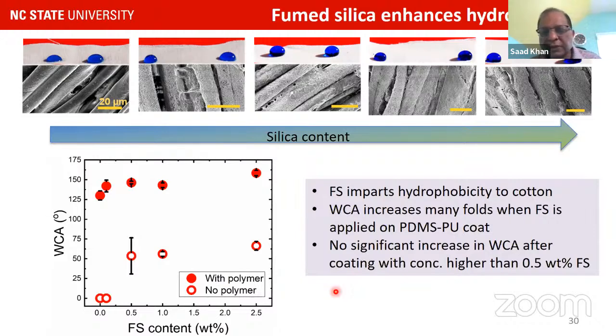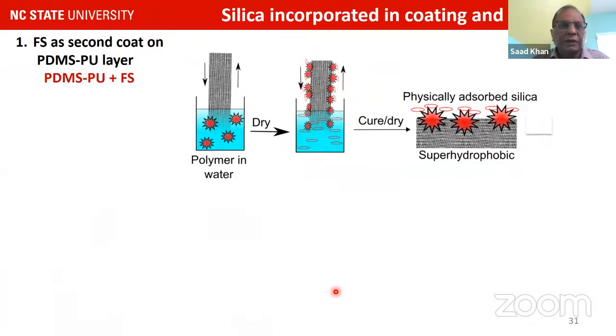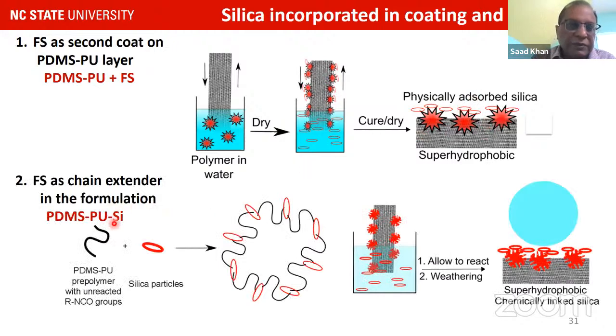So we wanted to see if we can modify our coating process to bring this fumed silica into the picture. We used 2 approaches. One is we just added fumed silica as a second coat. The idea would be we would coat it with the polymer or the block polymer, then apply the fumed silica, and look at the properties of this coating. The other approach was actually to integrate the silica in the formulation. So we would have not only a block polymer, but silica integrated in it. That way we could do a single coating or a double coating, and we'd like to see how this works.